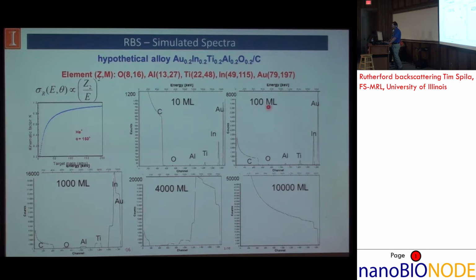As we go up to 100 monolayers, so we've increased it by a factor of 10, we have many more counts. The substrate is becoming harder to see, but we still have a lot of counts from our other elements. If we keep going thicker, now all of a sudden we can see in the aluminum, titanium, and oxygen that we actually have a flat top on our peaks. And that's information on the thickness. So we've got scattering from different points all throughout our film.